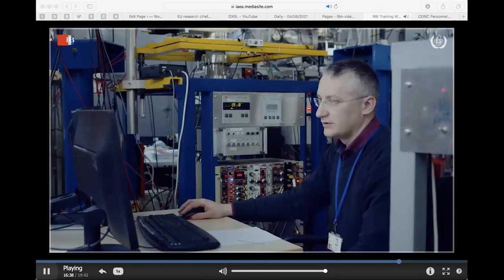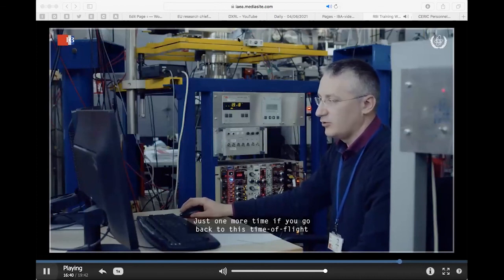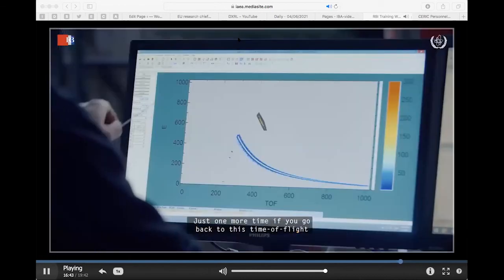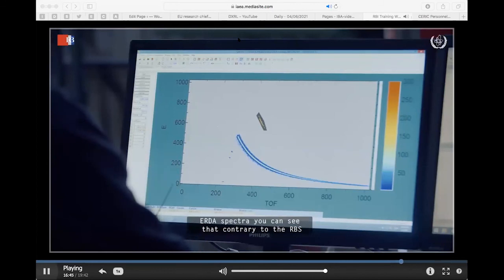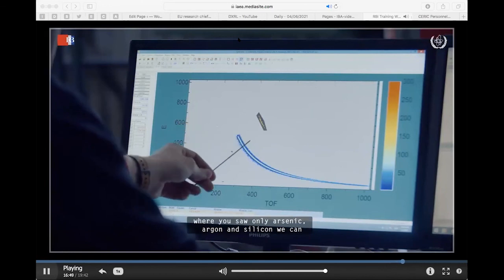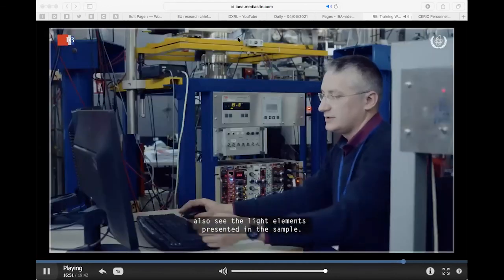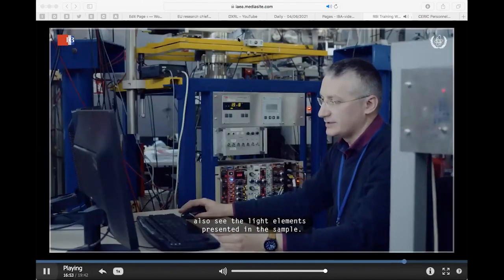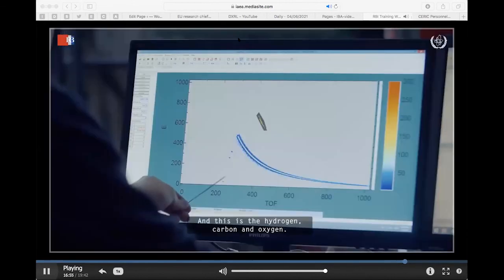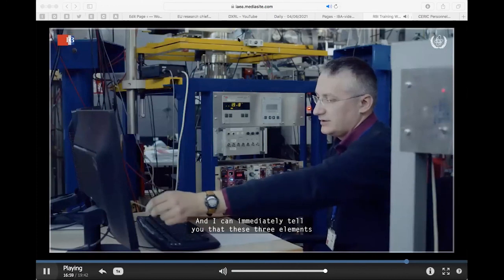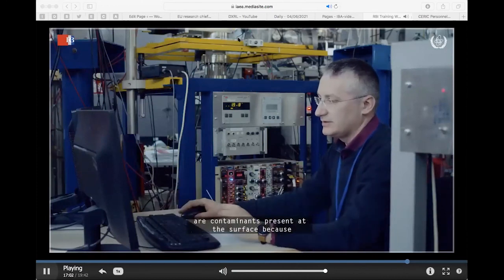Just one more time, if we go back to this time-of-flight ERD spectrum, you can see that, contrary to RBS, where you could see only arsenic, argon, and silicon, we can also see the light elements present in the sample. And this is the hydrogen, carbon, and oxygen. I can immediately tell you that these three elements are contaminants present at the surface because they are very thin.